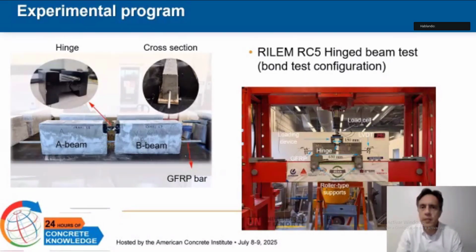On the right is the complete test setup in the universal testing machine. The specimen rests on roller-type supports that allow longitudinal movement and ensure a true hinge condition. A loading head connected to a calibrated load cell applies the load vertically at the hinge, enabling precise force measurement. This configuration produces a well-defined bond stress state that simulates real structural conditions more effectively than conventional axial pull-out tests.